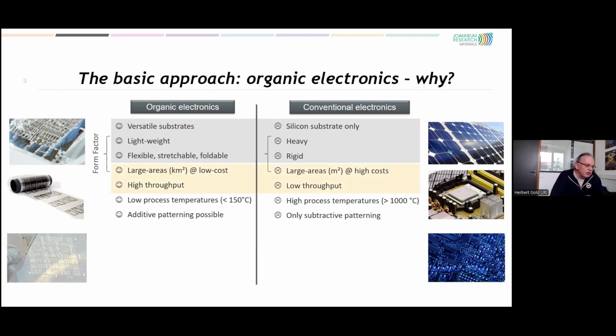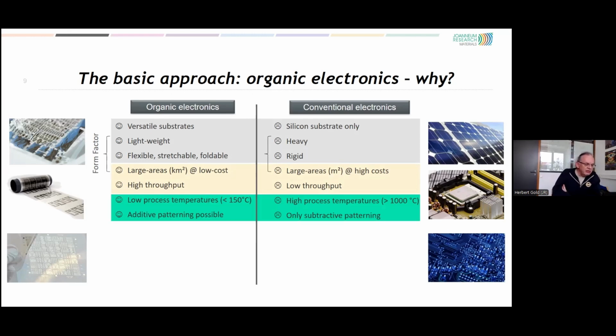Economically, we could produce this in large areas of square kilometers, even if we go roll-to-roll manufacture, and this would be at low cost. And also extremely in roll-to-roll manufacture, we could achieve a very high throughput. And concerning the environmental impact, the process temperatures could be, or must be, in the case of polymers, drastically reduced to below 150 degrees C, as compared to the high process temperatures. For instance, the oxidization in silicon would need more than 1000 degrees C.